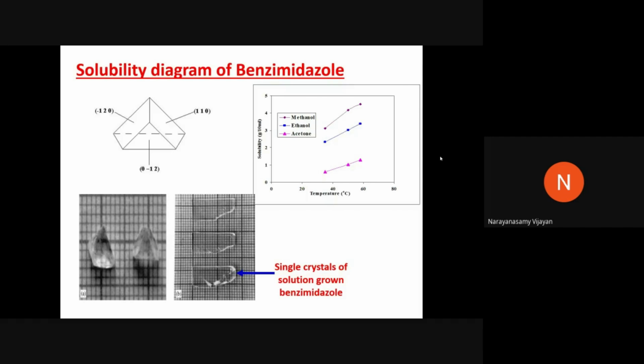I have taken a few examples. Benzimidazole is one of the excellent materials. It is an organic material, C7H6N2 is its molecular formula, and we can grow the single crystal by the slow evaporation solution growth technique. Sir C.V. Raman was handling and carrying an excellent solution-grown ammonium dihydrogen phosphate single crystal that had excellent piezoelectric applications. Like that, irrespective of the method or the material, we have to see the applications. Benzimidazole has excellent nonlinear optical behavior. We can compare this with the standard potassium dihydrogen phosphate single crystal, which shows one time of nonlinear optical efficiency. Benzimidazole shows approximately 3.5 times more nonlinear optical efficiency than potassium dihydrogen phosphate.